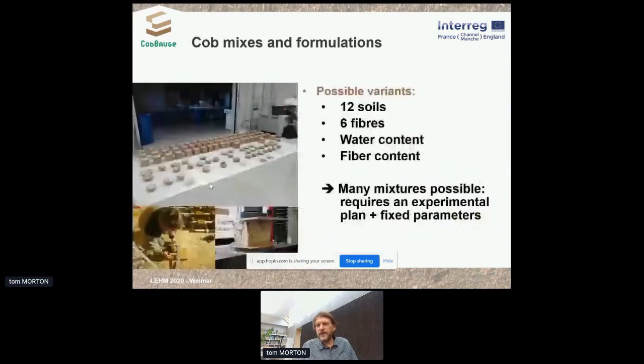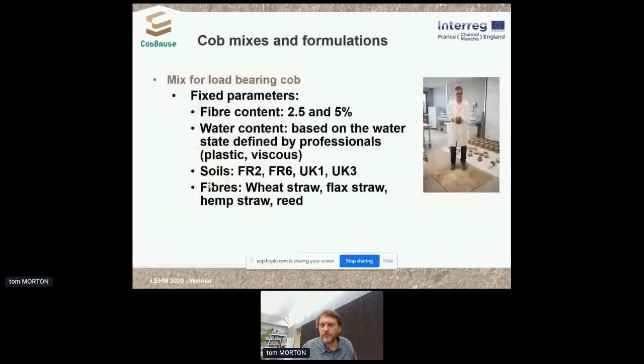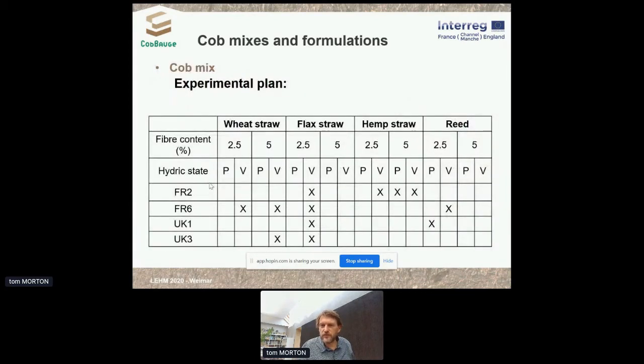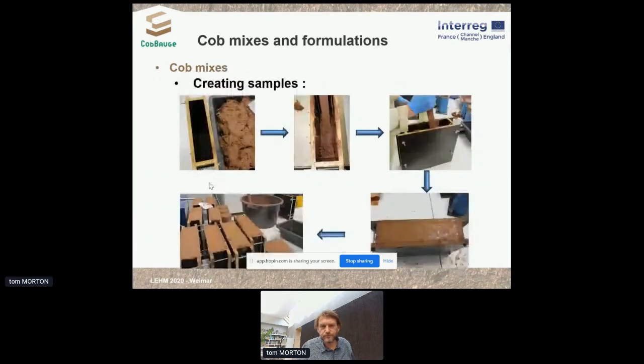And then we looked at many possible mixtures, varying the soil type, fibres, water content, and the amount of fibre, and we narrowed it down to a selection for further testing. The parameters for the load-bearing cob were fibre content between 2.5% and 5%, water content to get a plastic mix, soil type, and fibre type. And this is the range of tests we did for the cob.